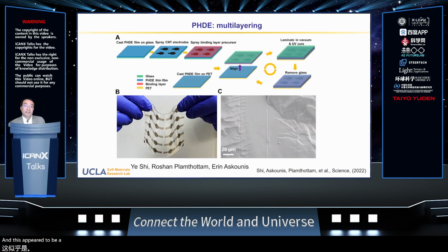The nice part about PHDE is not only that it has high actuation performance, but also that it comes from a precursor, a formulation of a bunch of compounds and liquid monomers mixed together. From that liquid formulation, we can process it in different ways, like the one shown here. The PHDE precursor is coated on different substrates and cured. Then we can also spray coat carbon nanotube electrode and a binder, so that when the PHDE films are stacked together, the binder glues the layers into what looks like a single sheet.